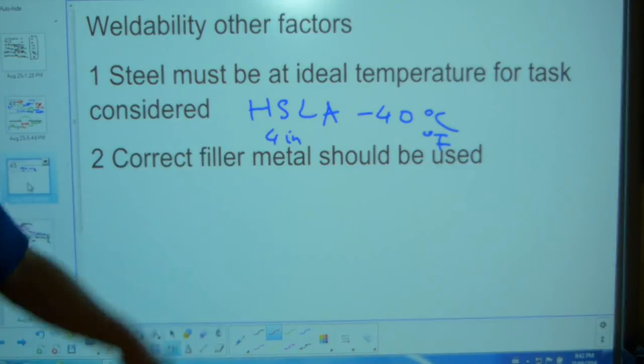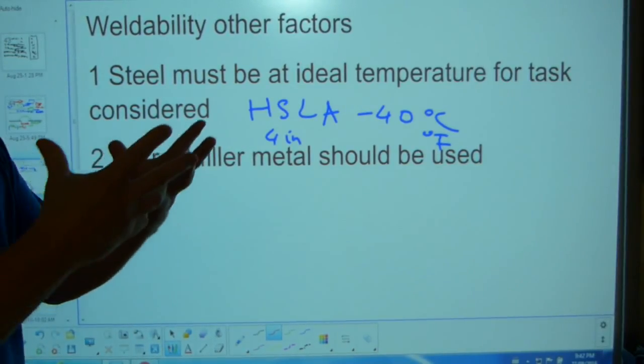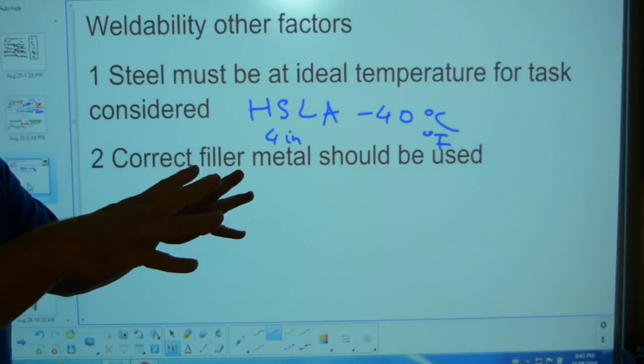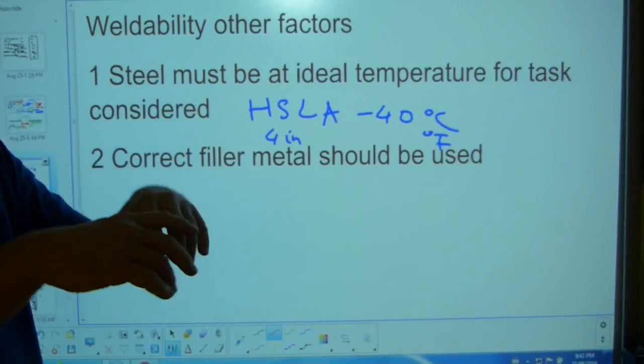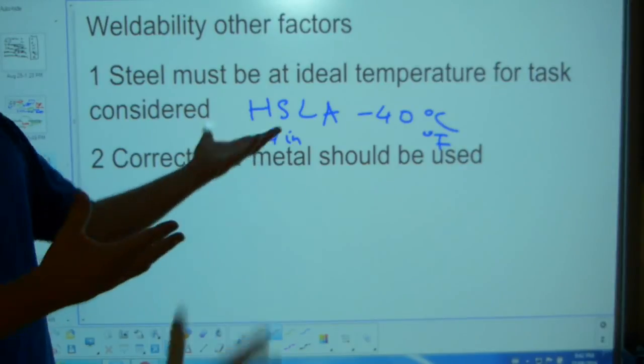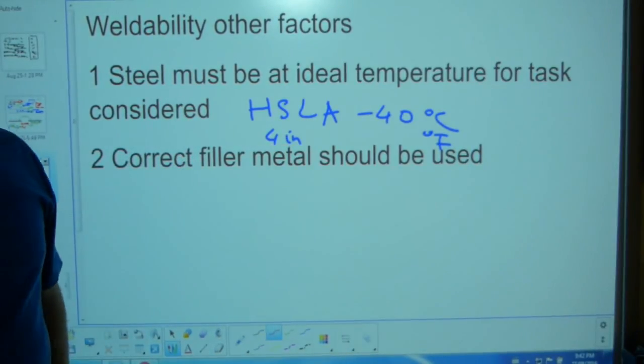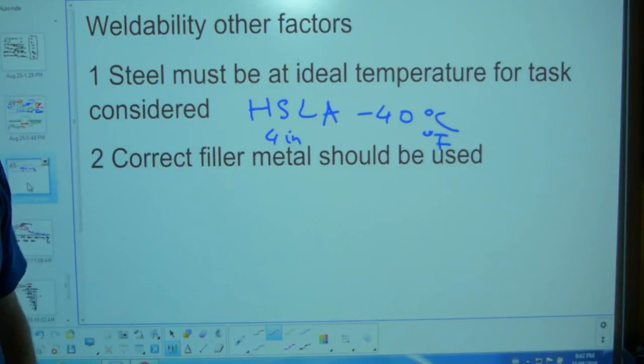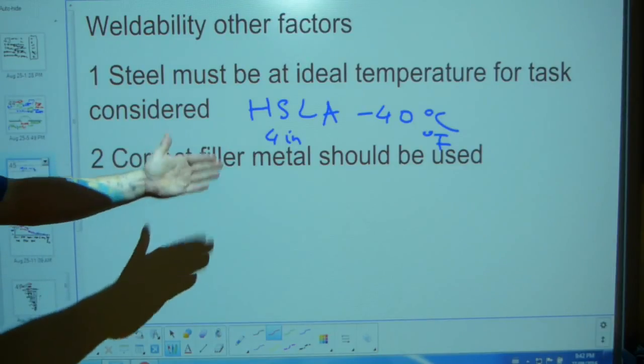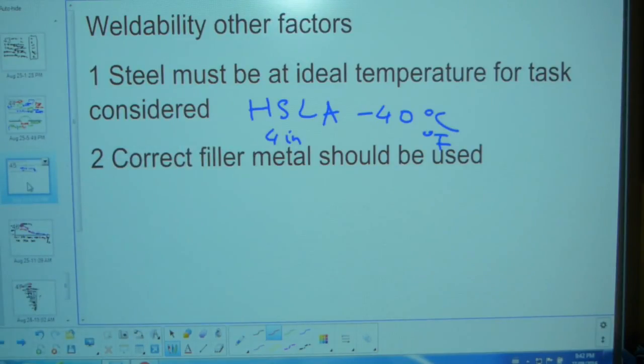If you have thick stuff to weld, it's going to be such a heat sink that the heat affected area will expand so rapidly, and the cold area will dissipate that heat so quickly, it's going to crack everywhere. So that also affects this temperature consideration. It is also a factor that affects weldability. And it goes without saying, the correct filler metal should be used, so the filler metal should have at least the same strength as the metals being welded together. But again, we're back to cosmetic welding, that also works.